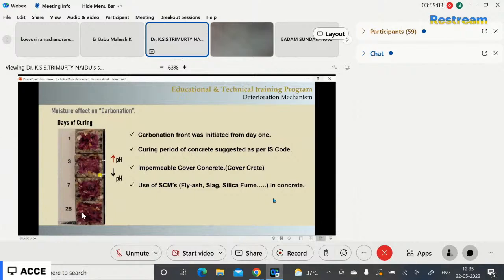This picture shows 4 concrete specimen cubes. Those specimens were cast at site and cured in outdoor condition for 1 day, 3 days, 7 days and 28 days to determine the carbonation depth of each specimen in real exposure condition. From this study, we came to know that the rate of carbonation is lower in the 28 days cured sample compared to all the 3 specimens. It means curing influences the carbonation rate. We can avoid such carbonation in the concrete by curing the concrete as suggested by the IS code.